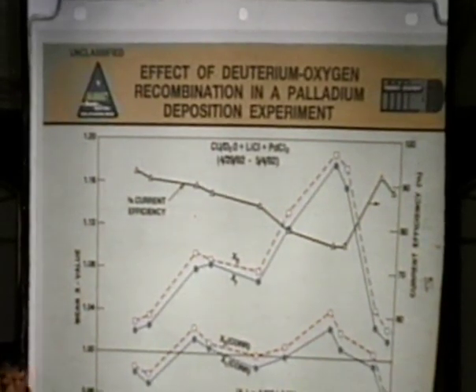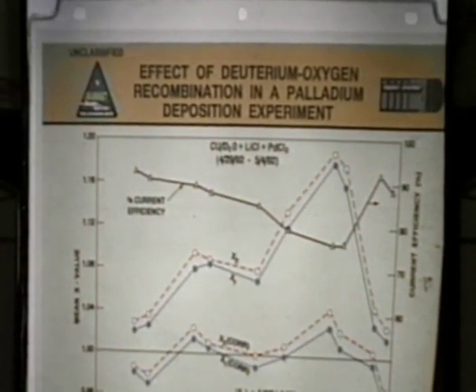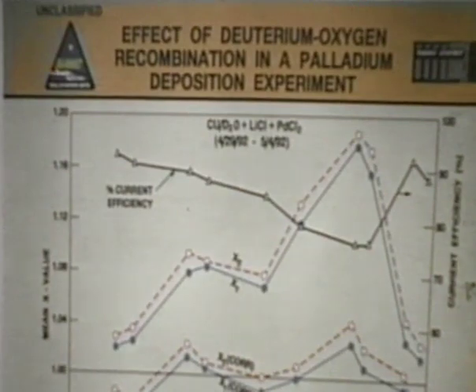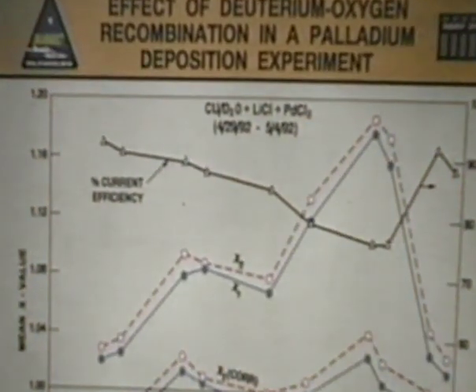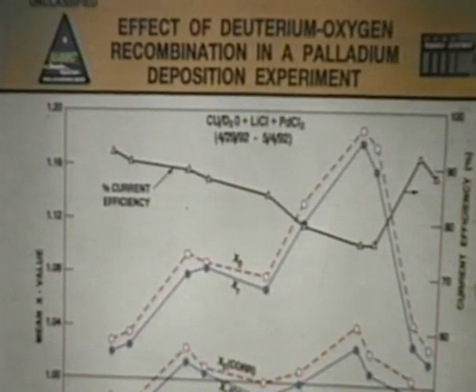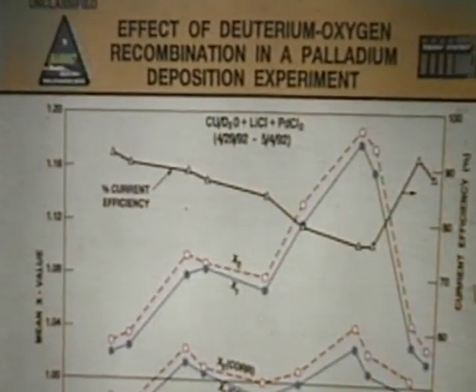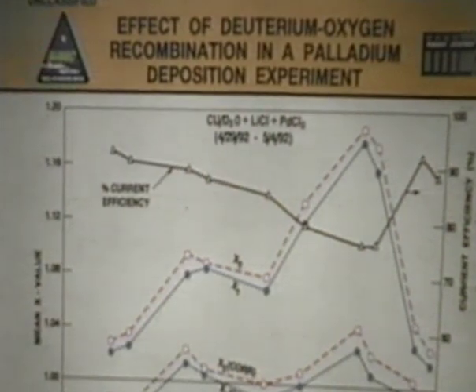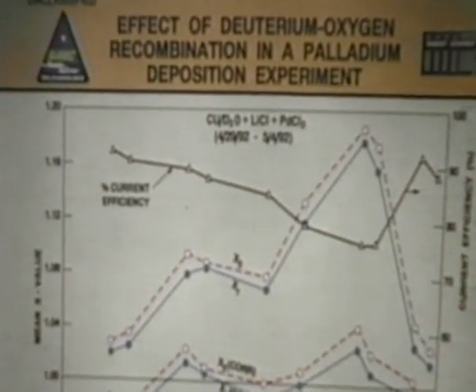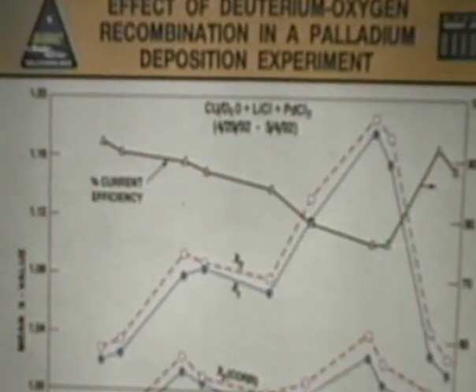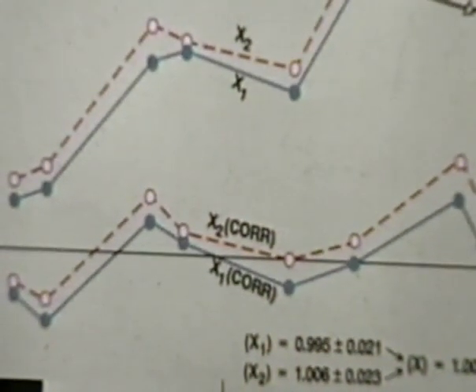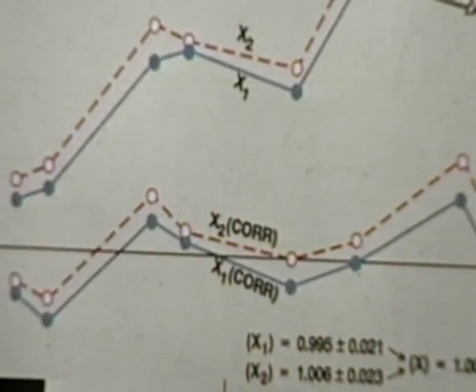One argument that critics raise is there could be recombination. Now, we always check for recombination 2 ways. We measure the gas coming out of the cell at the time we measure the excess heat, and that always agrees with Faraday's law within 1%. And we also measure the volume of D2O that we add each day. So we know how much D2O we have to add to make up. So we have a double check to make sure there's not recombination. And we've never seen recombination with a palladium cathode that's fully submerged.